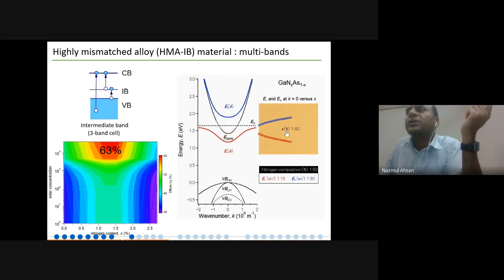So this simulation is from 0 to 3%, but within the 0 to 3%, this shows something very interesting. If you look more and more, you see the valence band is doing nothing. Everything is happening in the conduction band. For example, this is 1.8% in gallium nitride arsenide. Now this is the original conduction band of your gallium arsenide, but in this new material you have a new band. This is the red band, and also you have a second band. This is the blue band. And the interesting thing, the more nitrogen you put, the more these go down and these go up.